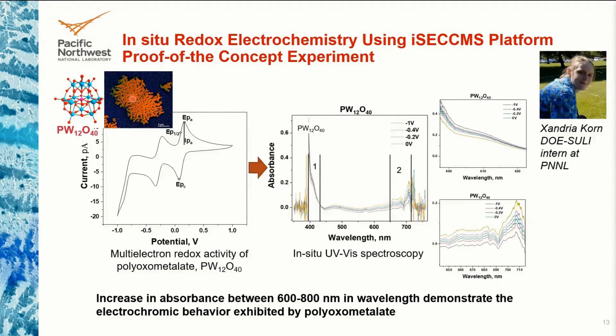reaction. But another interesting property is that it has a particular UV-Vis spectroscopic signature. So we can coat the ITO surface with a POM molecule and we were able to measure the spectroscopic signature at a different potential range. In this case, we were able to see a distinct signature in the UV region and also in the high visible region, in between 650 to 700 nanometer wavelength region.